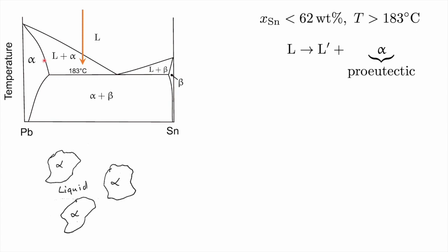And in the process, because the alpha is poorer in solute, the liquid will become enriched in tin compared with the alpha. You know, the liquid can dissolve more of tin than the alpha can. And therefore, as the material cools under equilibrium conditions, the composition of the liquid will follow this phase boundary, and the composition of the solid alpha will follow this phase boundary. So the liquid is getting richer in tin as solidification proceeds. So initially we have liquid going to enriched liquid, right? Liquid which is enriched in tin, plus alpha, which we say is pro-eutectic alpha because it's formed above the eutectic temperature.